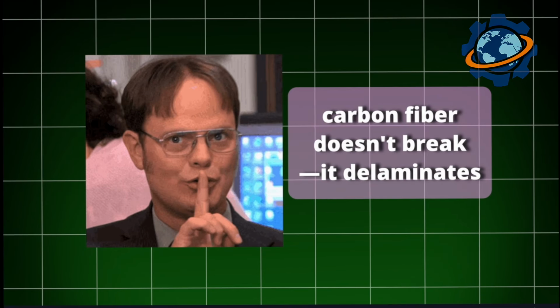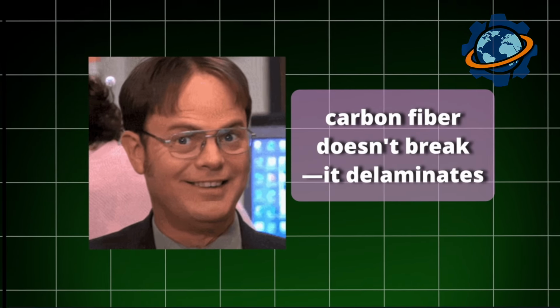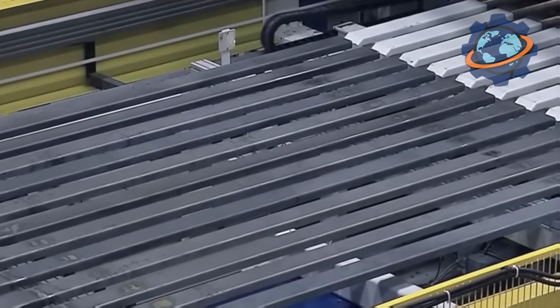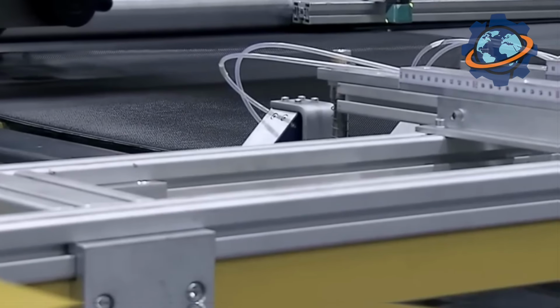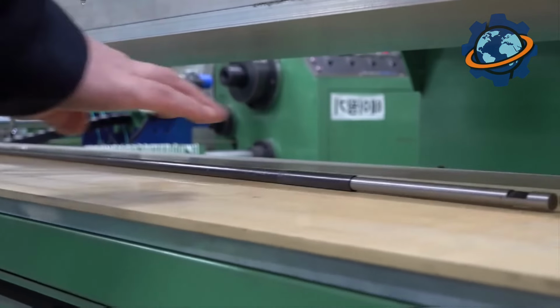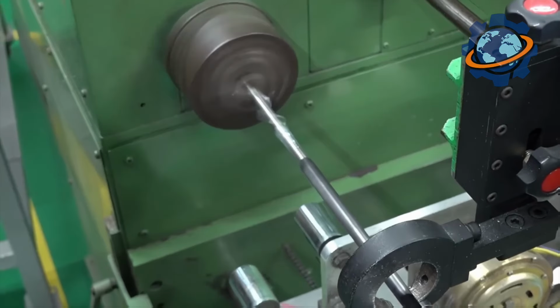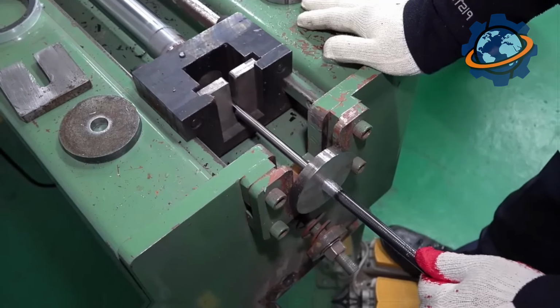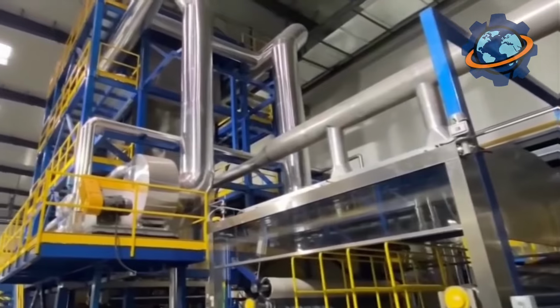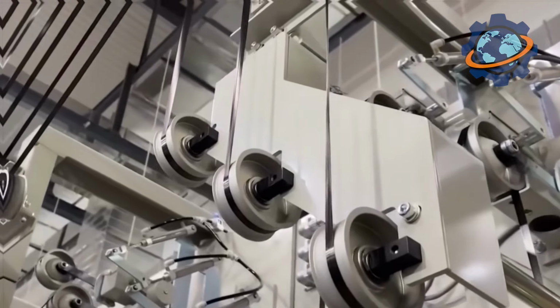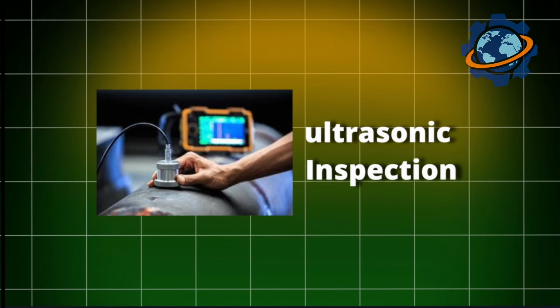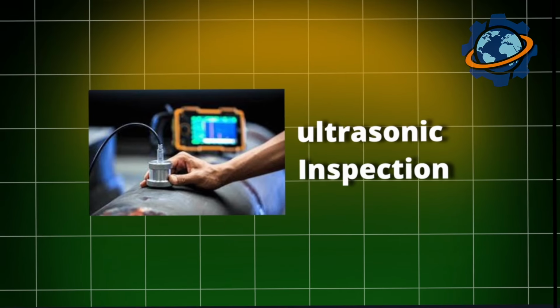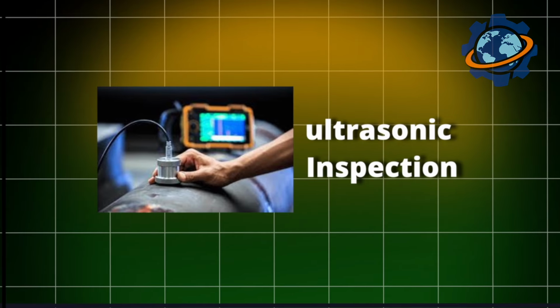So here's the secret promised. Carbon fiber doesn't break, it delaminates. Unlike metal fracturing through crack propagation, carbon composites fail through layer separation. Impact damage creates barely visible surface dimples, hiding extensive internal delamination, while composites require ultrasonic inspection after any impact. That failure mode makes recycling challenging.